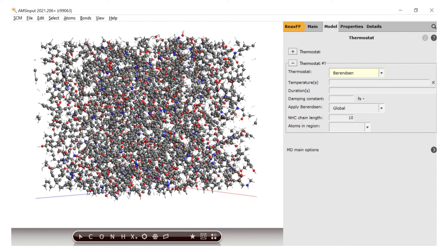We begin the temperature program with a quick annealing run from 298.15 up to 600K and then down to 350K. The heating up period is going to take 100,000 steps and the cool down period is going to last 200,000 steps. The damping constants will be 100 femtoseconds.